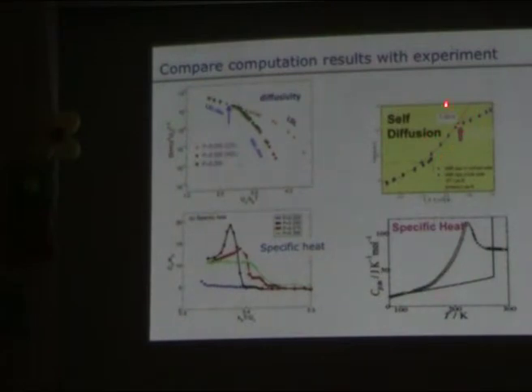So this is what experiment had before for the nanopore. You can see for specific heat, there is a maximum over here, because there is only one line that an experiment can get. We have no idea which part of the phase diagram they are in. And then if we compare to the simulation, in all our data, because we can search everywhere in the phase diagram, we know exactly what happens in each part of the phase diagram. You can see in the one phase region, we actually didn't see this response function maximum. So this is definitely not corresponding to the two-state phase. However, in the supercritical region, you can see that we have this specific heat maximum. So this is pretty much similar to what experiment observed.